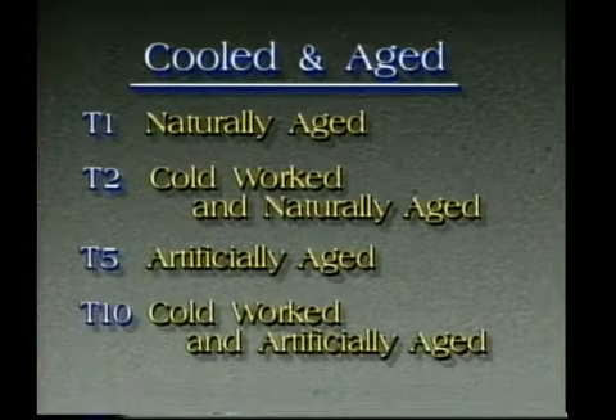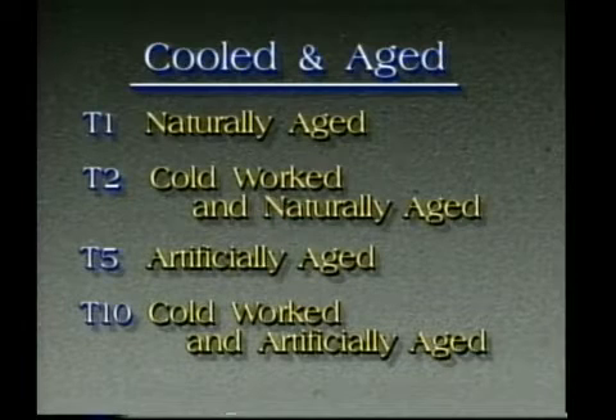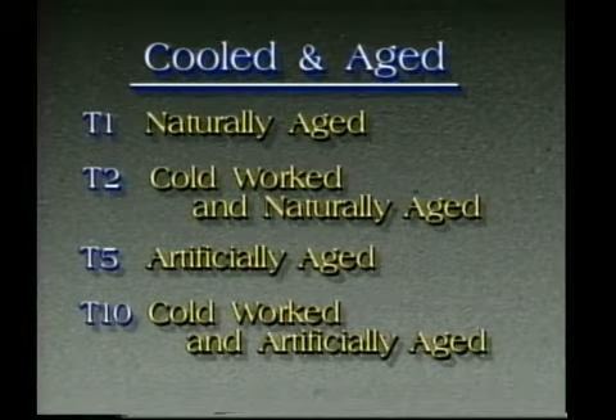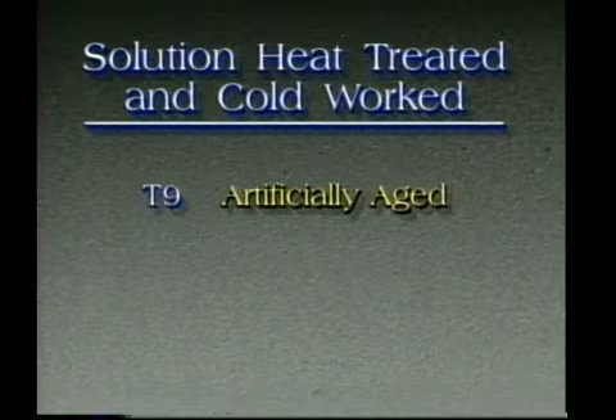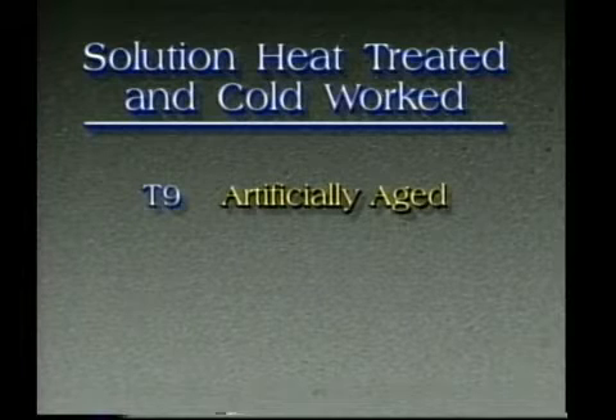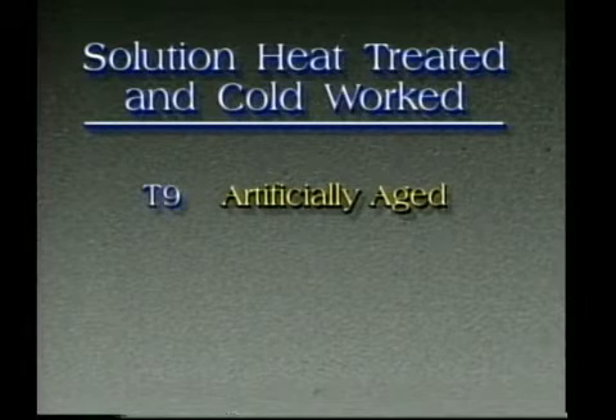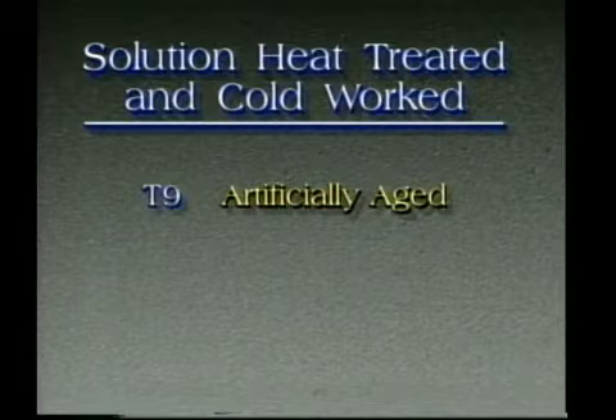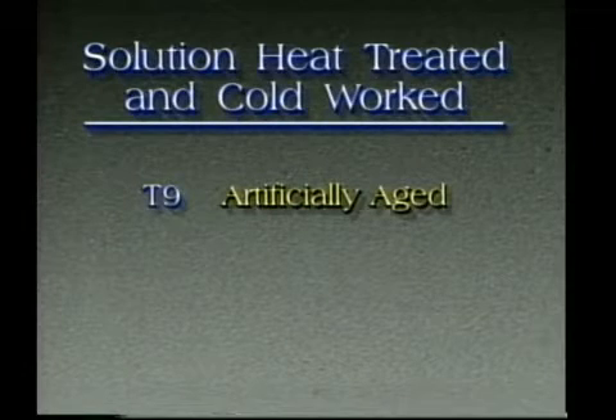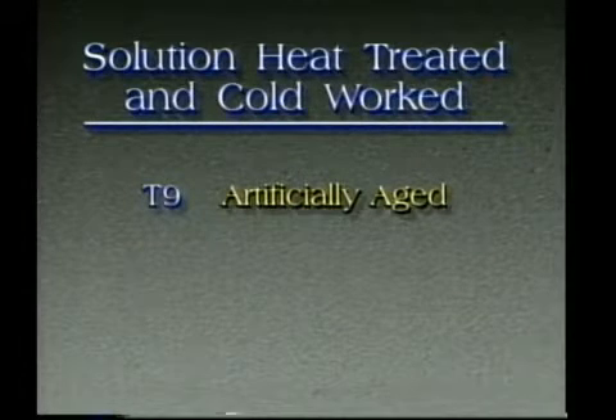The T10 temper is cold worked and then artificially aged. The T9 temper is cold worked after solution heat treating, quenching, and artificially aging. It applies to products such as wire, where the cold work after aging improves the strength. Let us now review the differences between similar tempers.